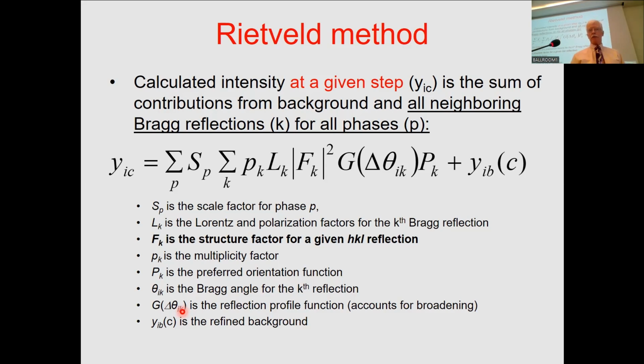Remember what's built inside the Rietveld method. It calculates the intensity at every step, but built inside it is F. And where does F exist? It exists at a delta function. So if you're applying the Rietveld method to a disordered material, to a nanomaterial, you're making huge approximations that you don't even know about. They're in the back of your mind, or maybe not even in your mind.